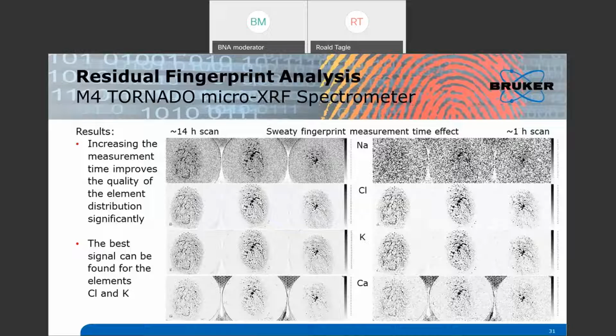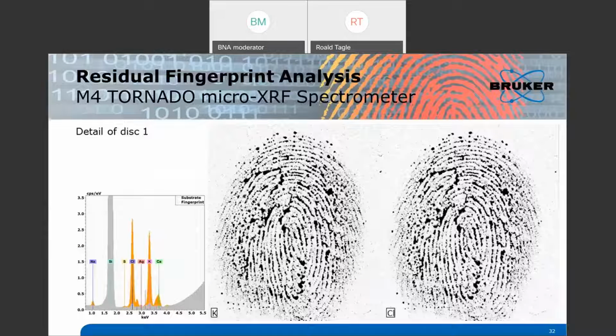However, the contrast is much better in this case from what we can see here for the elements potassium and chlorine. If we just grab two of these fingerprints and display, and plot the potassium and the chlorine fingerprint elemental distribution contrast, this is really just elemental distribution. Behind these images, you have just an intensity matrix of these two areas, or for these two elements.